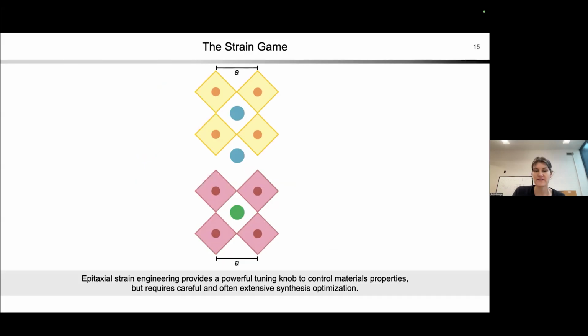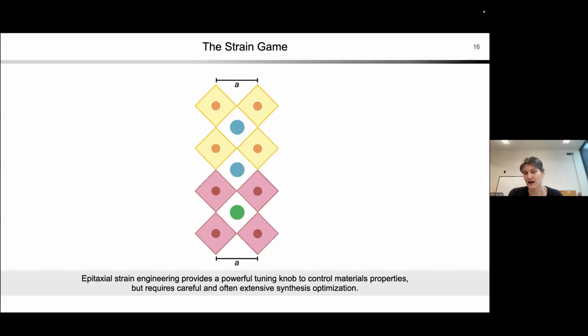One of the things that can make it hard to optimize these materials is something called epitaxial strain. I mentioned that this is a thin film of a nickelate compound, which is deposited on top of something else, some kind of support platform. If you have these two materials, like what I'm showing here in this cartoon, they all have their lattice constants, right? It's a crystalline material, and there are characteristic distances spacing out all of the atoms. If these two materials have similar symmetry, similar shapes, both cubic in this case, let's say, and they have very similar lattice constants marked by this ruler A, then you can put one on top of the other without any problem, right? There are some other technicalities, but in principle, it works very well, and everything is nice and happy.